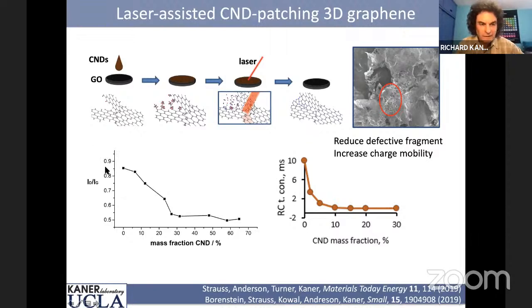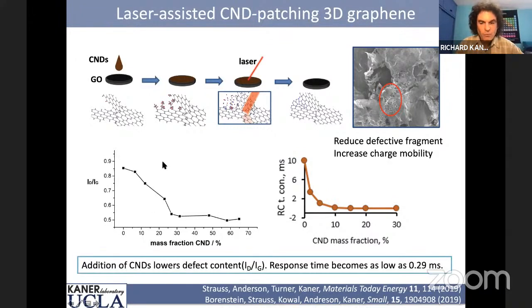And you can look at the Raman spectrum and you can show that things can improve up to about 25% mass fraction. But probably the most interesting thing is you can reduce the time constant. And we've gotten the time constant down to less than 1 millisecond, down to about 0.3 milliseconds. And so now you can think of these things as possibly doing line filtering and other things where you need very fast electronic responses.